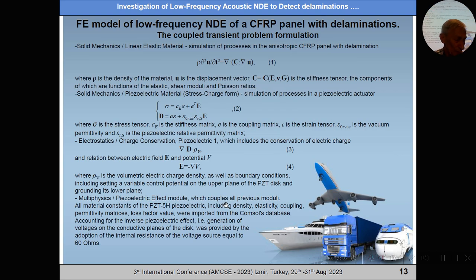The problem of wave propagation is solved by a COMSOL Multiphysics model including solid mechanics with linear elastic material describing wave propagation in the panel, solid mechanics with piezoelectric material in stress-charge form describing the piezoelectric actuator process, and electrostatic charge conservation to describe the relationships between the electric parameters of the process.